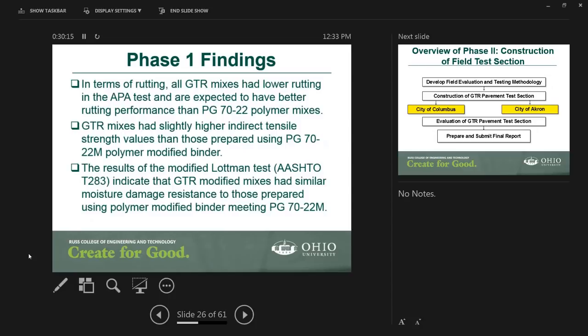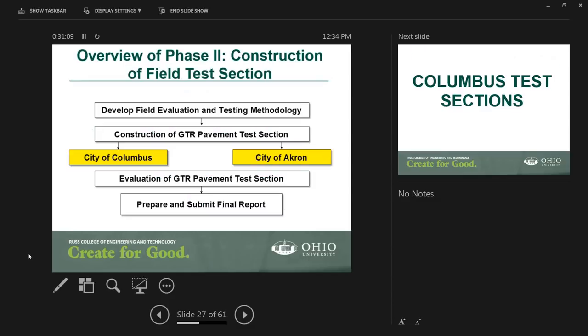In terms of rutting, the GTR mixes had a better rutting resistance as compared to a polymer modified binder meeting 70-22. In terms of the AASHTO T 283 results, the GTR mixes had slightly higher indirect tensile strength, and also similar TSR values, indicating a similar resistance to moisture damage as compared to a polymer modified 70-22 binder. And again, all comparisons are made to that polymer modified 70-22 binder that we obtained in this study.